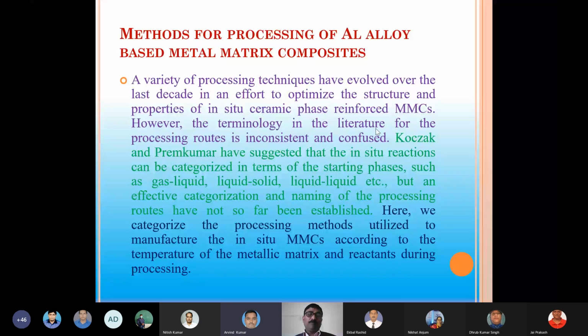In that case, you have to take aluminum as the matrix material and keep it in the furnace, and it will melt. Then you add the titanium in the raw form, and titanium will react with the aluminum and form titanium aluminide. At the same time you add graphite powder, or activated charcoal, and then all three will react and form the titanium carbide at the higher temperature, so as to avoid the aluminum carbide, which is brittle in nature. So you will get the proper properties or proper strength.